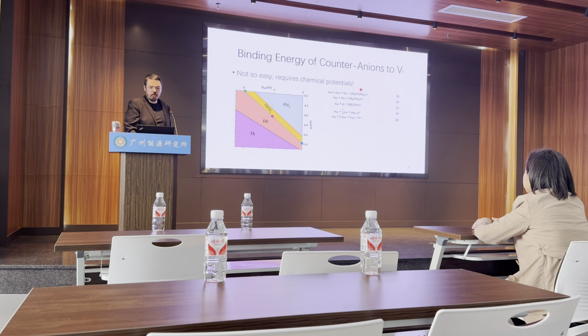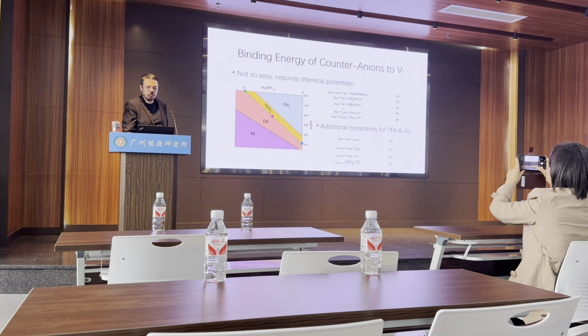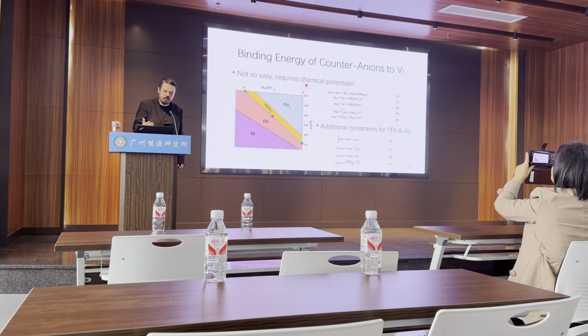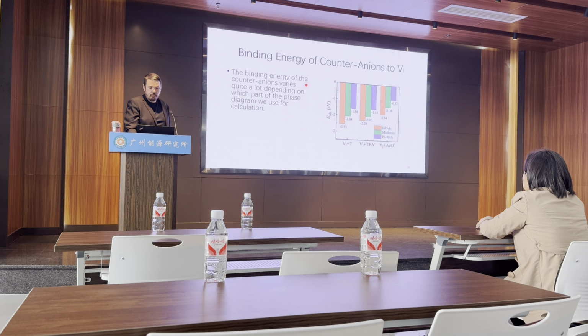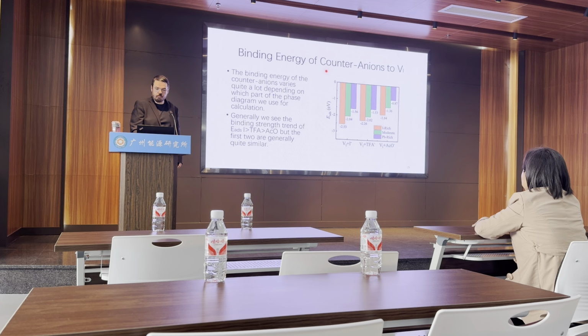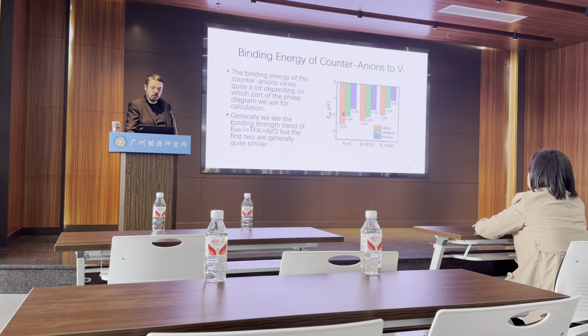We can also do the binding energy of the counter anion, and this is not so easy because you have to work with chemical potential. So you have to go to boundary conditions, you have to calculate the phases. I won't go into too much detail, but basically I made up some new boundary conditions to make sure I can compare directly the iodine to the acetic acid and TFA. That's the whole point of this slide. When we look at the result, you can see that depending on the chemical potential, our absorption energy is changed by almost 1 eV, which is a pretty big change. But in general, we see the iodine and the TFA have similar binding strengths. Acetic acid is weak relative to them.